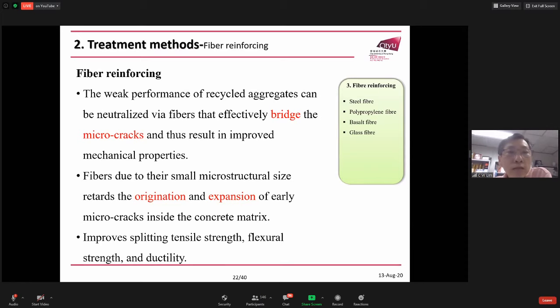Now, we move to another treatment method, which is fiber reinforcement. We can use steel fibers, polypropylene fibers, basalt fibers, and glass fibers. The weak performance of recycled aggregates can be neutralized by using fibers that effectively bridge micro cracks and thus result in improved mechanical properties. Fibers, due to their small size, retard the origination and expansion of early micro cracks inside the concrete matrix. It improves splitting tensile strength, flexural strength, and ductility.